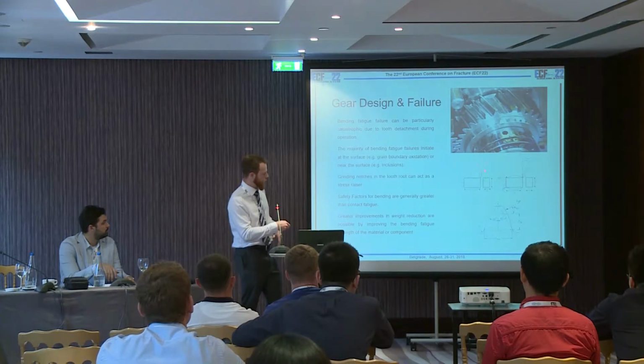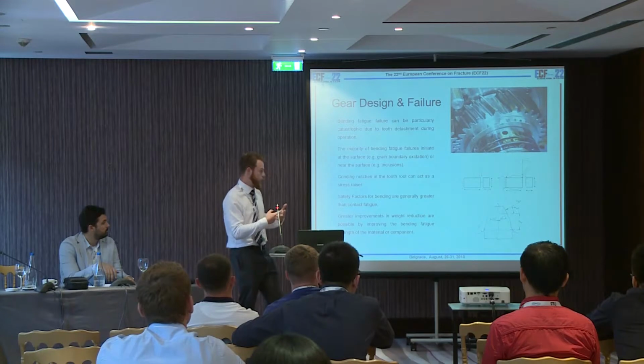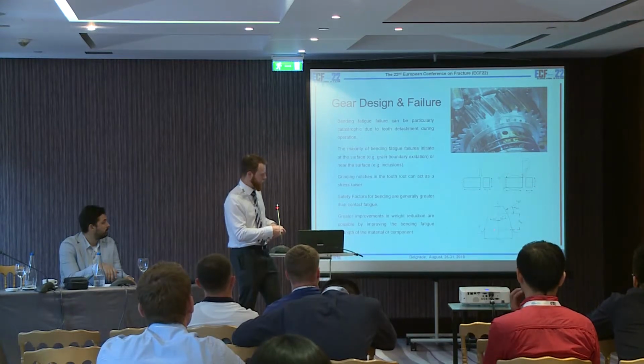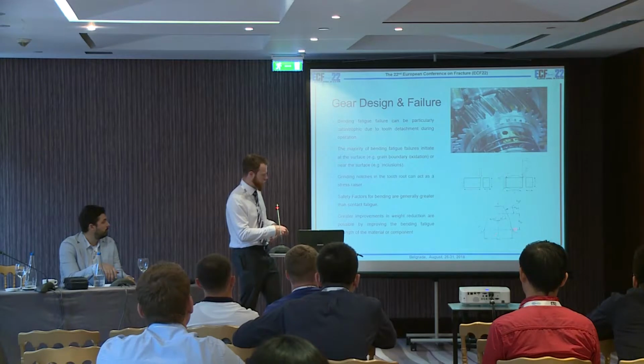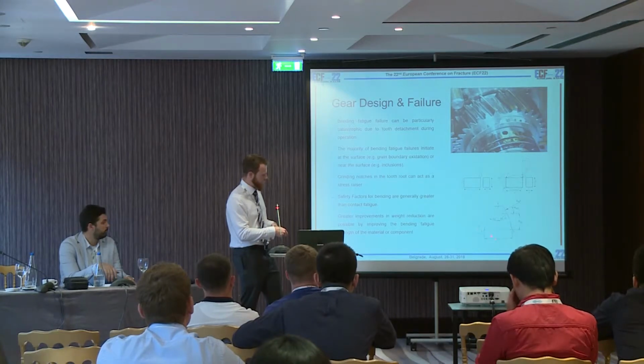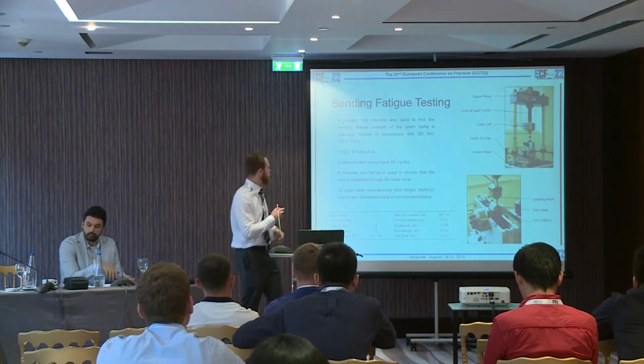We look at the load appearing at the highest point of single-tooth contact, so when only one tooth pair is in contact, and we calculate the second moment of area at a 30-degree tangent plane where the tooth roots are. If we've got the load coming in from the right-hand flank here, we'll see a tensile stress appearing in this tooth root here. The crack will then grow towards the neutral axis. That neutral axis is changing as the crack grows, and at the end it will then turn up towards the opposing tooth root and end up in complete tooth detachment.